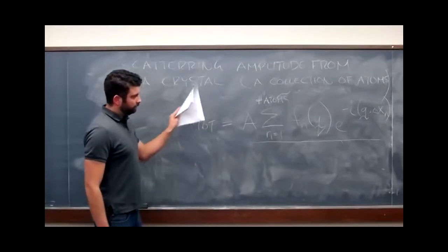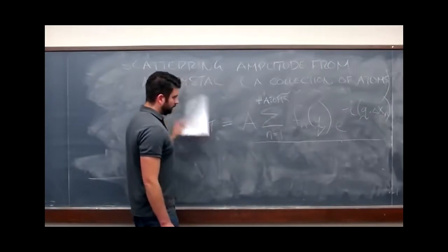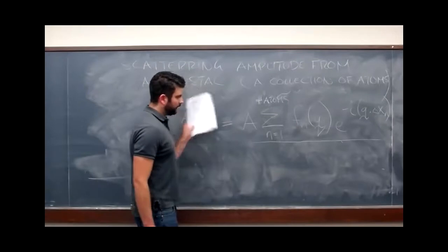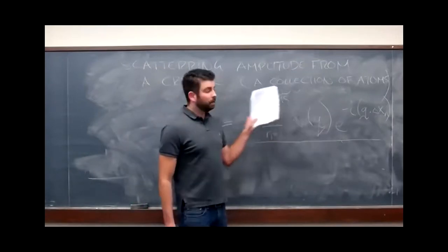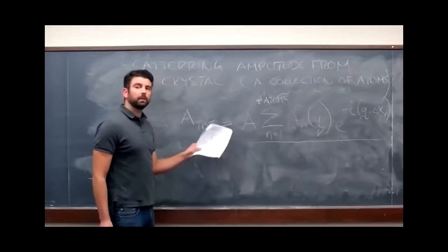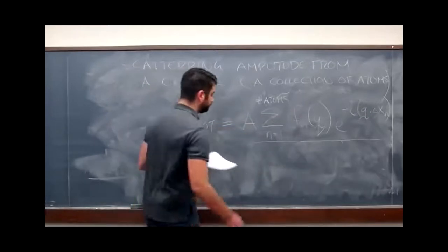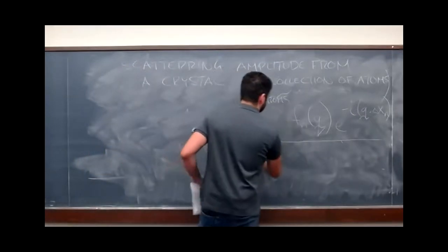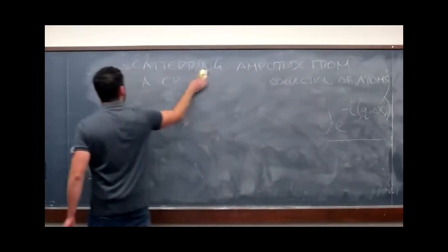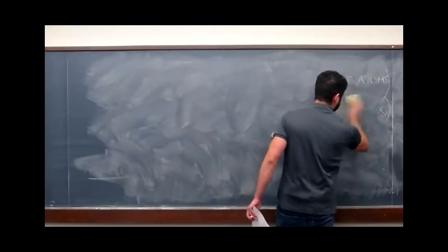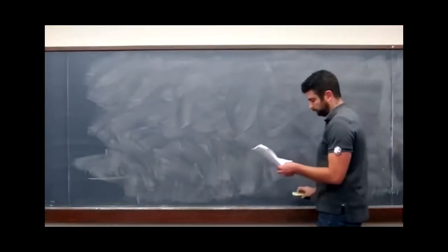And so what I really want to emphasize is don't limit yourself to things like analytical solutions that have been calculated in the past. If you want to know what the scattering power is from a crystal, let's say a dislocation or a defect in it, all you have to do is program in those positions where atoms sit in a dislocation and calculate the scattering amplitude yourself. This is something that can be pretty easily programmed into a computer. But now we're going to go a little bit farther.